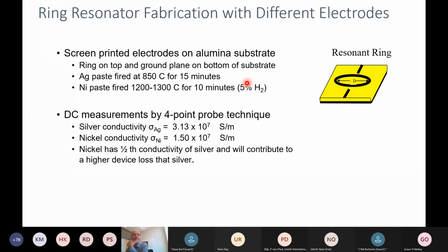In this case, I'll show a comparison between silver paste and nickel paste. You wonder why I would ever study nickel paste. We had some projects on multi-layer ceramic capacitors where the industry really moved toward nickel. And as they're pushing these decoupling capacitor frequencies higher, there's a lot of interest in nickel because it not only has a lower conductivity, but it also has a permeability that could contribute maybe to the performance of these devices.